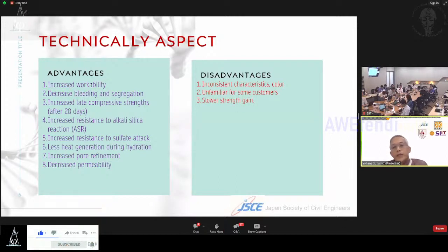So the third disadvantage is the slower strength gain. Because fly ash causes slower strength gain, for early strength concrete requirements, material engineering must be carried out, for example by adding chemical admixtures. In our factory, we use type D admixture, which is a retarder, and we use superplasticizer, and sometimes we use an accelerator.